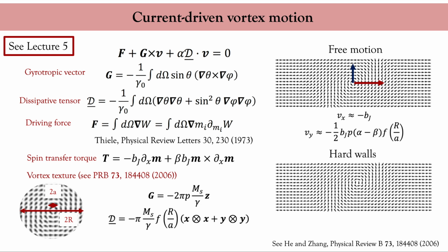Of course, we still have the longitudinal and transverse forces applied by the spin torque, but they are balanced by the reaction of the edge. This reaction cancels the vortex Hall effect so that only the longitudinal velocity survives. A small calculation indicates that in this case, the longitudinal velocity should be proportional to the ratio between the non-adiabaticity and the magnetic damping, which is pretty much similar to what we obtain in the case of the one-dimensional magnetic domain wall.